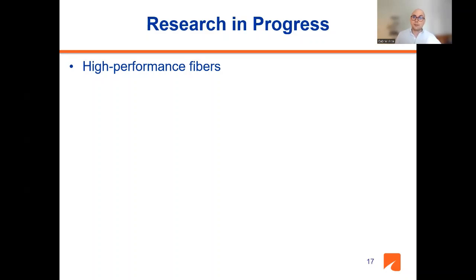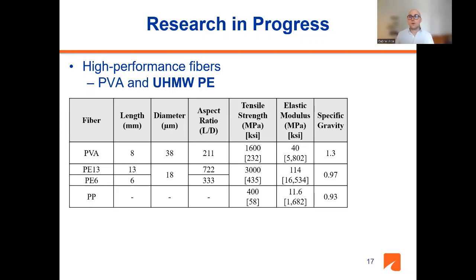We are testing some high performance fibers. These are PVA, which is a traditional fiber used in ECCs, but also ultra high molecular weight polyethylene fiber. Just to give you a flavor for what the properties of these materials are, the PVA fiber that you use for ECC has a length of 8 millimeters, a diameter of 38 microns, and an aspect ratio of about 211. The tensile strength is comparable to that of steel fibers, a specific gravity about 1.3.